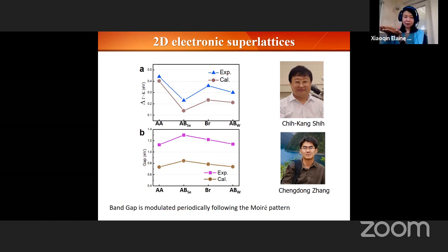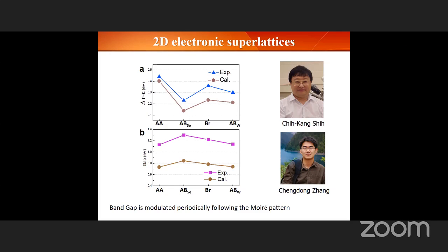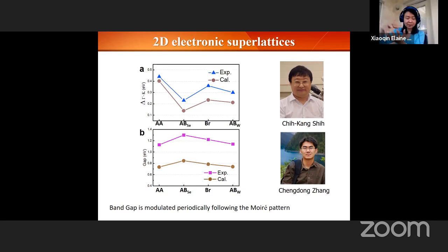I think it does. First of all, the potential in the vertical direction and the lateral direction is different. In the vertical direction, they're basically bounded by the substrate and the vacuum, the air. So that potential is pretty sharp. The thickness of these monolayers is already on the order of 0.7 nanometer, and there are wave function extensions through this 0.7 or 1.4 nanometer. If you stack two layers, it's a little over one nanometer. In the lateral direction, it is softer. So it will change the specific energy levels the electrons and electron-hole pairs can occupy. So this is what we know.